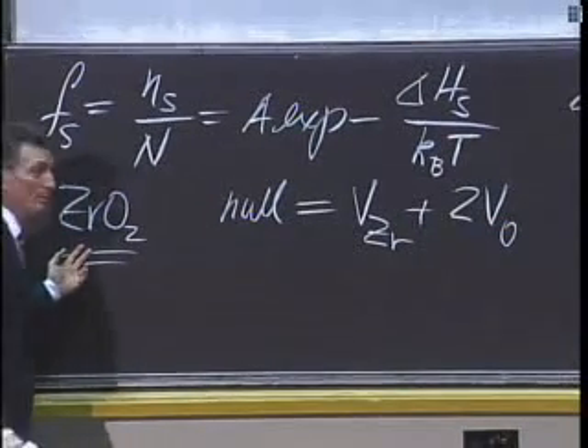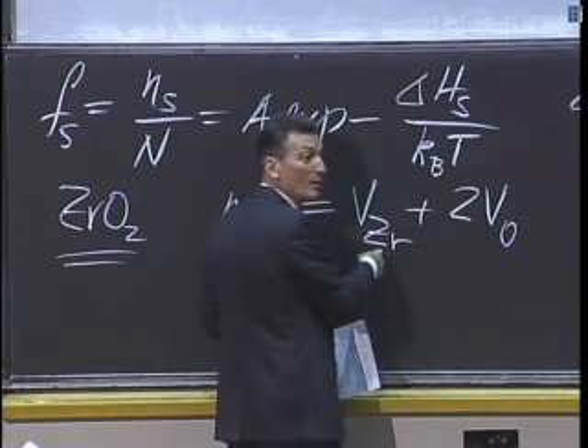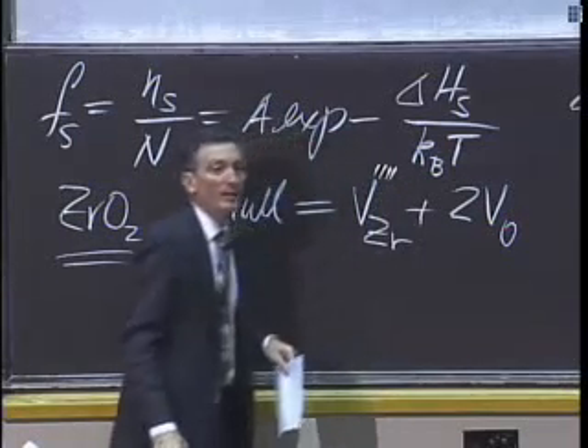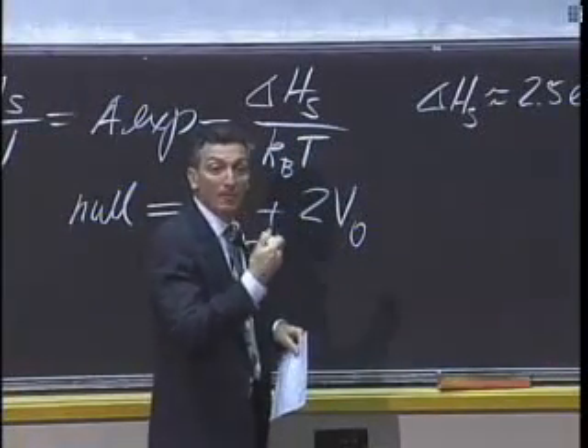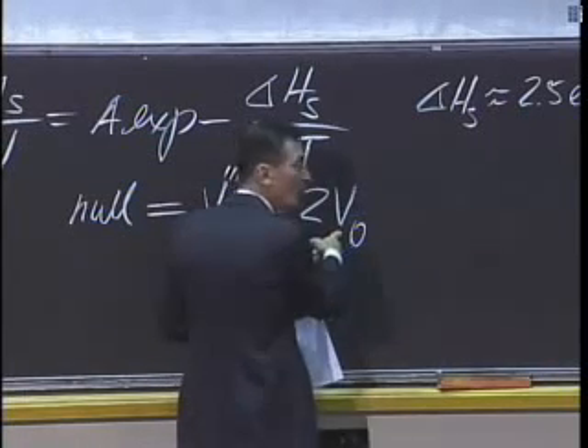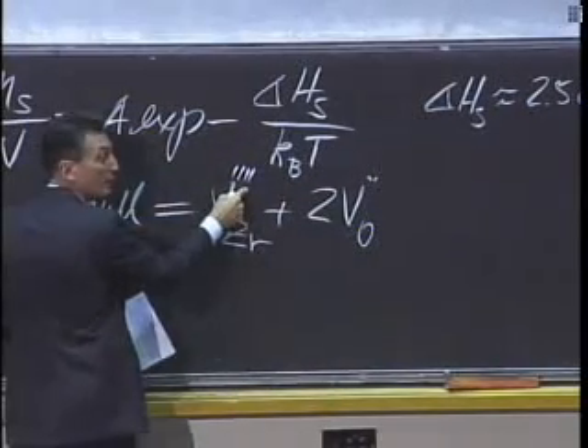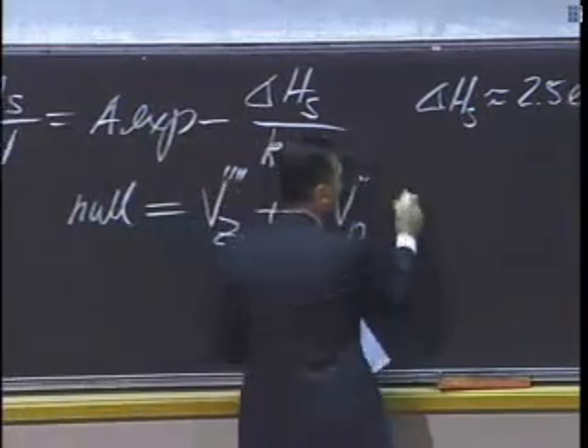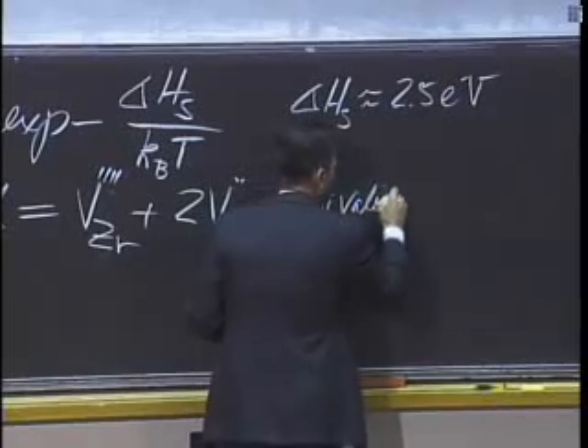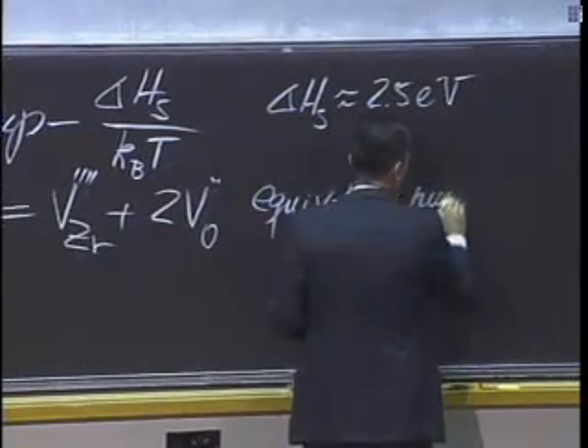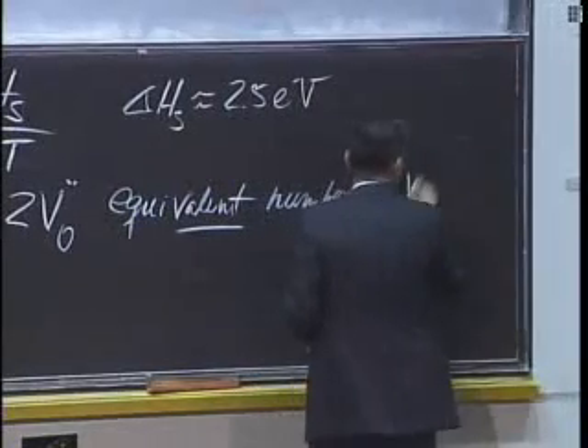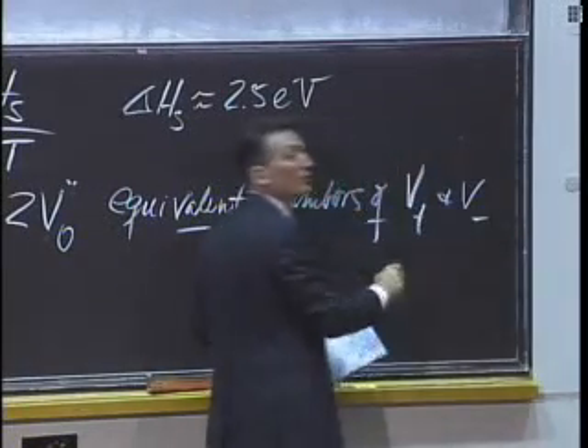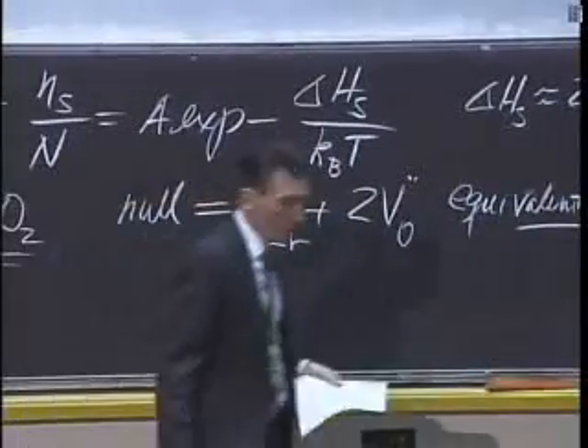Nothing counts here, okay? Because what's the local charge? This is 0 in a land of +4, so it's apparently -4. And every oxygen is a 0 in a land of -2. All of the oxide ions are -2. This oxide ion vacancy is 0. 0 in a land of -2 is +2 apparently, so I have -4 apparent, 2 times +2 apparent, charge neutrality, and this is now equivalent numbers of cation and anion vacancies. Very cool.